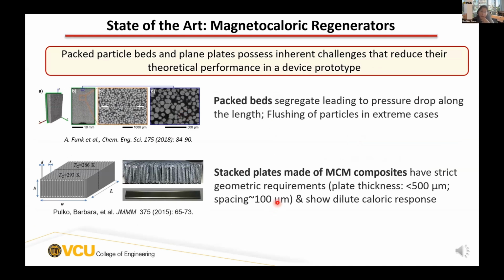The other way of making it is by making stacked plates using MCM composites—magnetocaloric particles with binders. Because of the presence of the binder, they show a dilute magnetocaloric response, and they also have very strict geometric requirements. For instance, the plates have to be less than 500 microns thick, spaced 100 microns apart, which in ideal circumstances is not very easy to make.